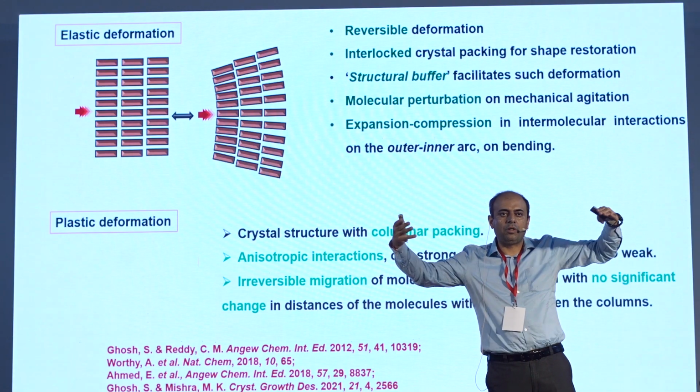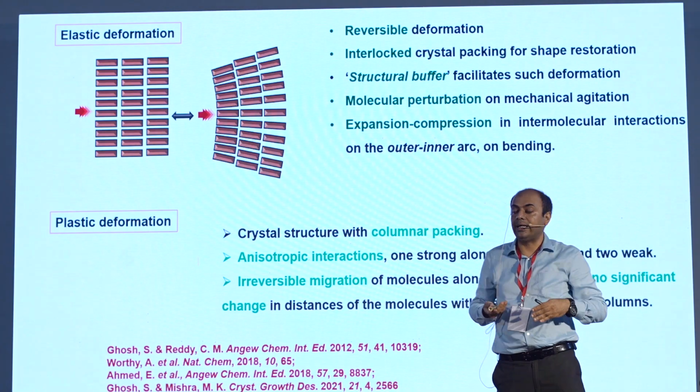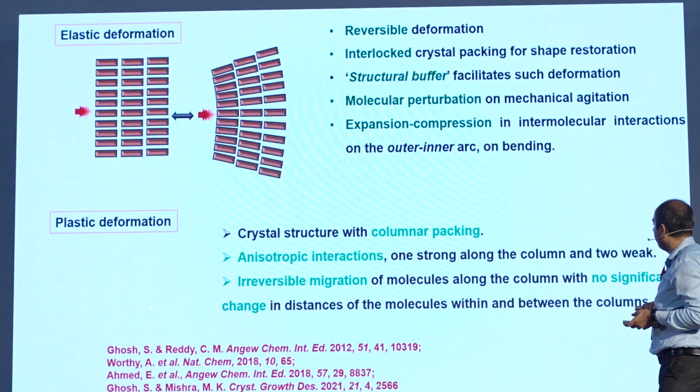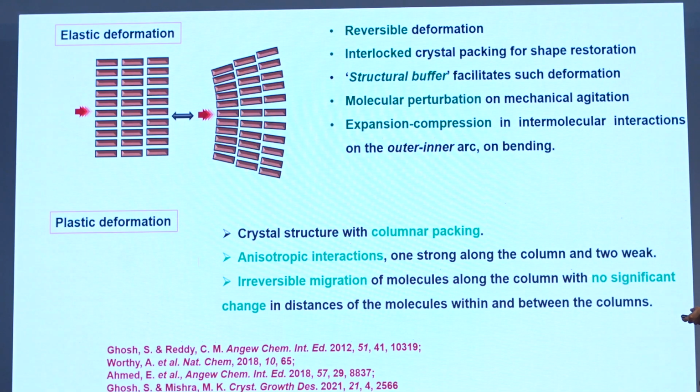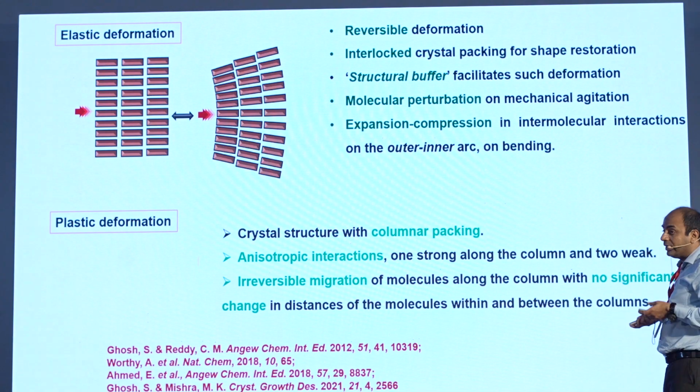You can displace molecules when you have weak interactions, but you cannot break the strong interactions. So the molecules in one layer are held by strong interactions, in the other directions are held by weak interactions, so that gives rise to the plastic deformation, and you have this irreversible migration of molecules, and during this process,